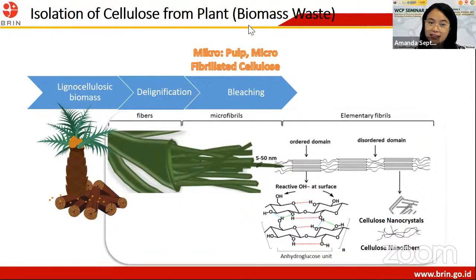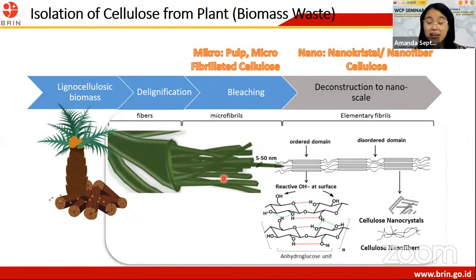So first, usually the lignocellulose biomass, we treat it by chopping and grinding it, and then we do the delignification. Mostly we use sodium hydroxide, and then we do the bleaching. After the bleaching, we usually get a pulp, or microfibrillated cellulose. If you can see from this figure, the fibers consist of hundreds of microfibrils. Then, if we deconstruct each individual microfibril in accordance with the ordered crystal domain or disordered domain, we can get cellulose nanocrystals with high crystallinity, or cellulose nanofibers, using several approaches.